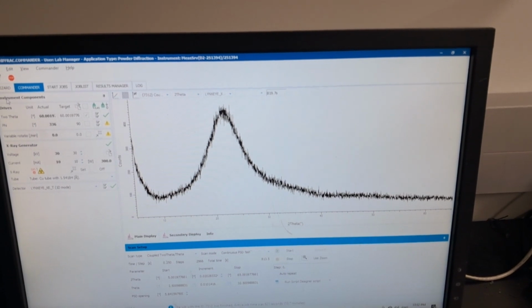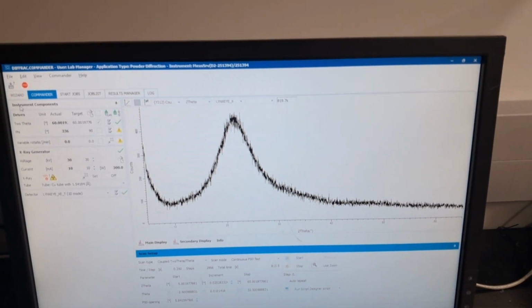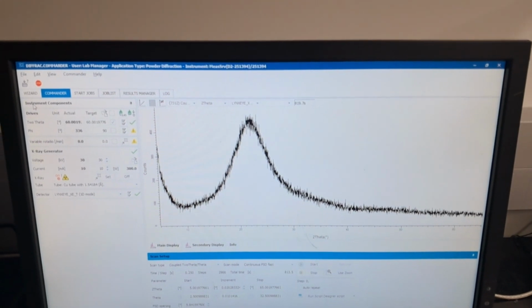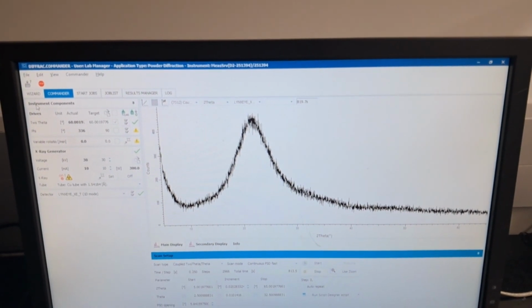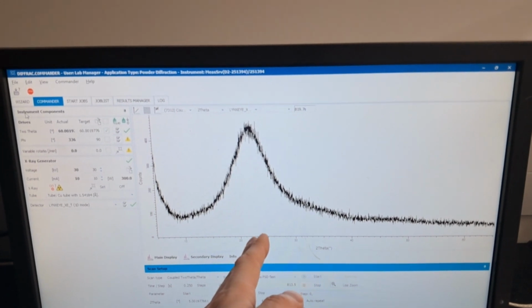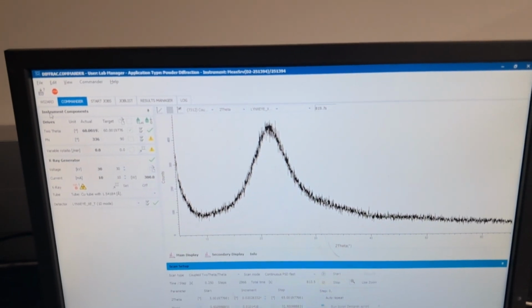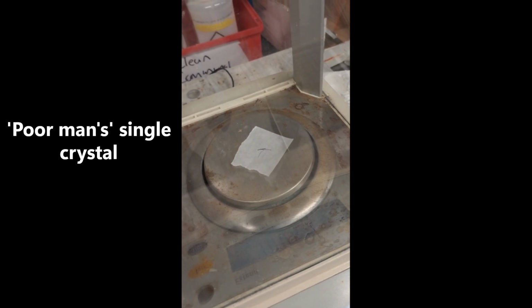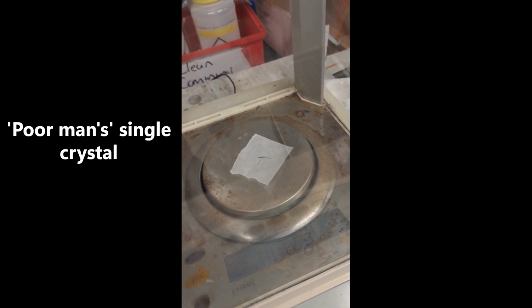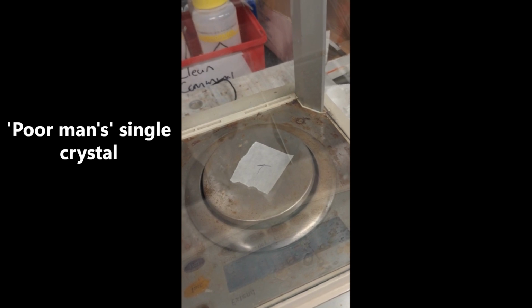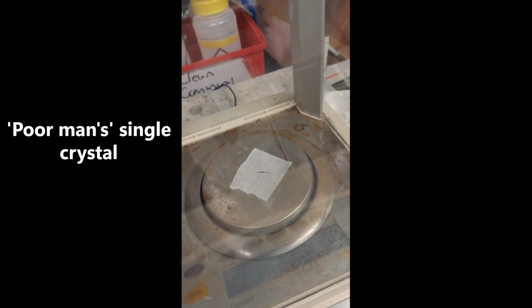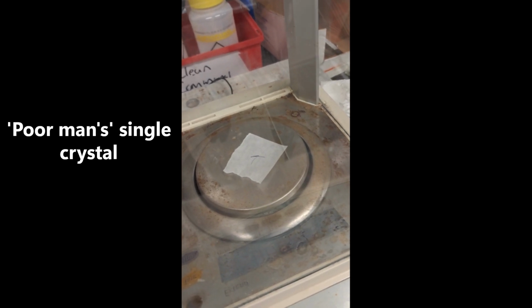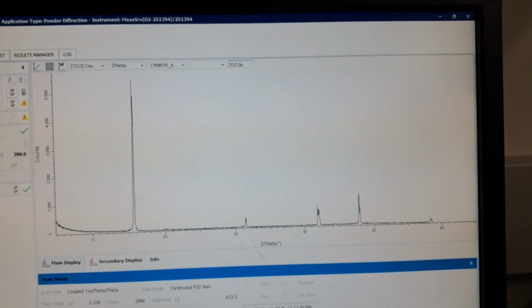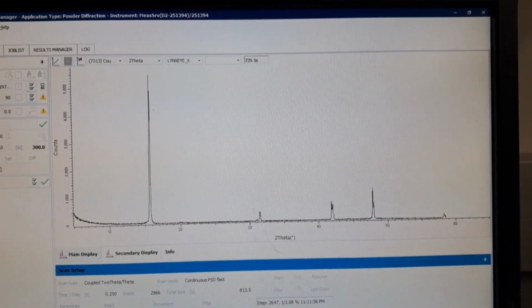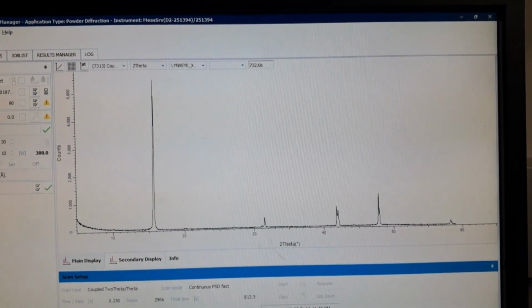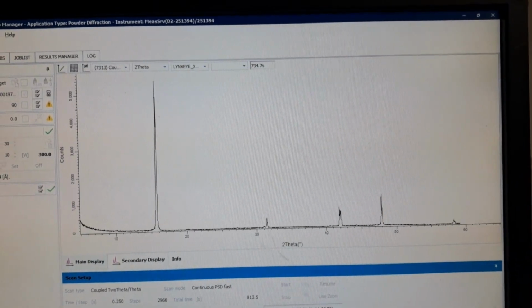You should see the amorphous region prominently between 10 to 30 2 theta when using a copper source as we did, likely with the highest intensity approximately in the 22-23 range. For a reference point, it may be worth running this material as single crystal XRD samples to know which planes are present within the pattern to get a feel for the preferred orientation effect. This scan is still going, but I have 3 one-dimensional scans run on the mount, and you can see that there is clear preferred orientation effect.